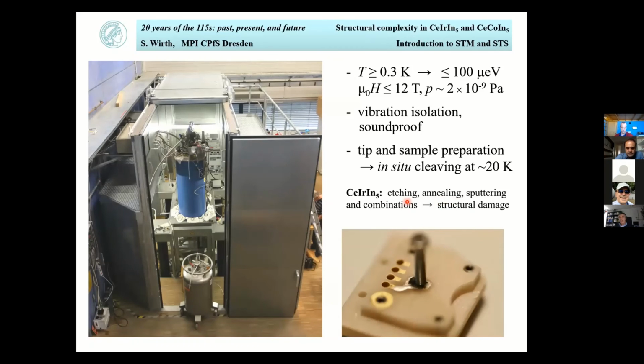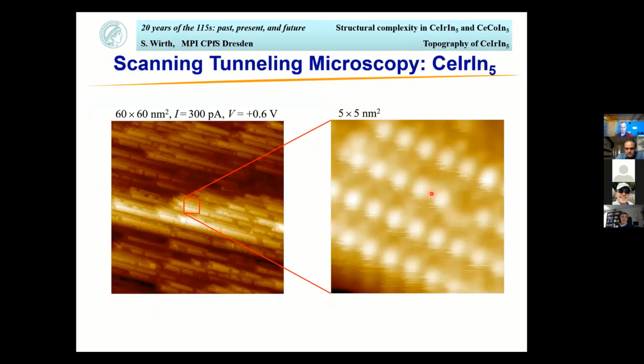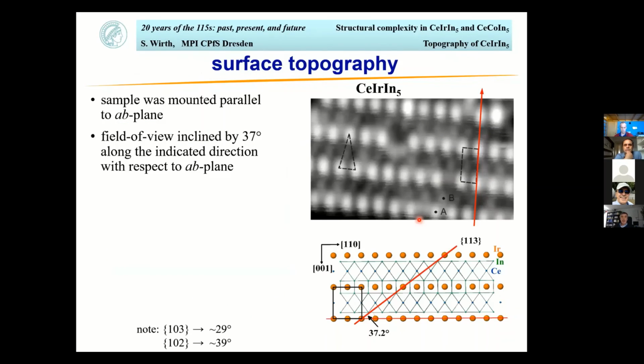If we did etching, annealing, sputtering, or any combination thereof, we did see structural damage. For instance, in the case of the annealing, some indium segregated out, so that's no good. So this is an overview picture of the atomically resolved iridium surface, but let me directly go into this picture here. The sample was actually mounted with the AB plane perpendicular to the tip. So we come down with the tip from the top, and the AB plane is perpendicular to the tip. So that's this plane here.